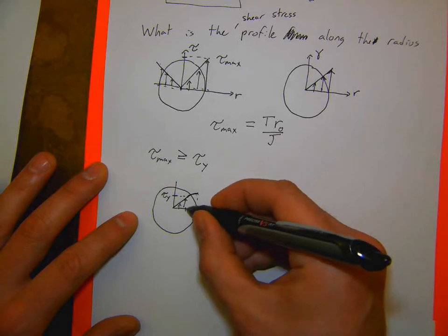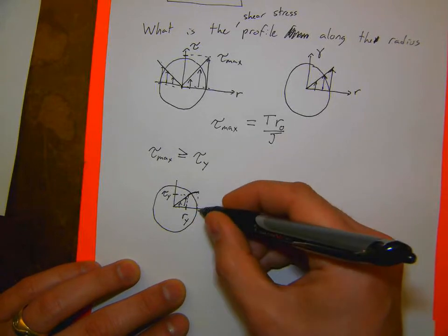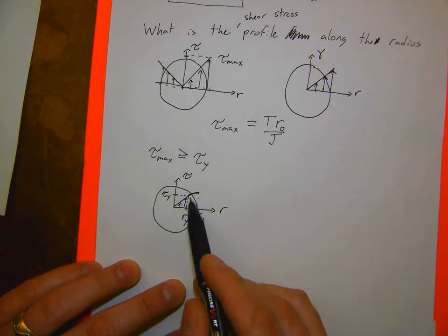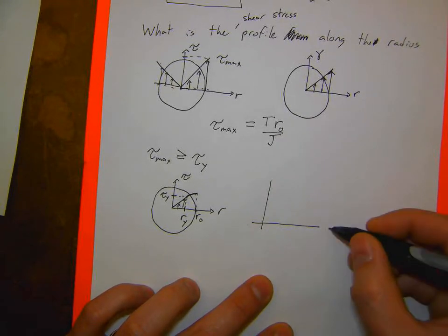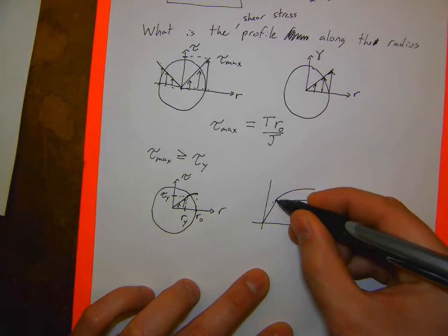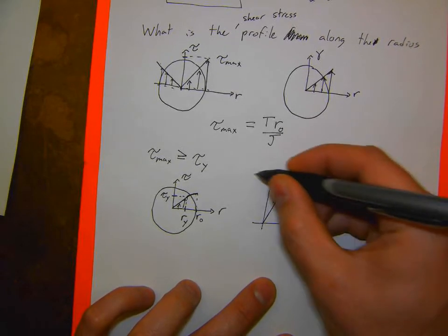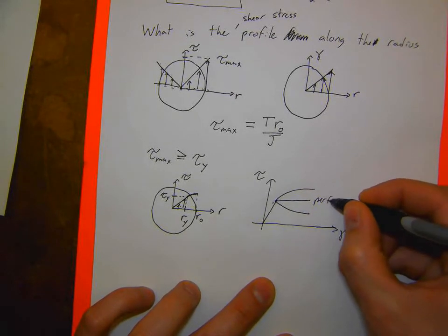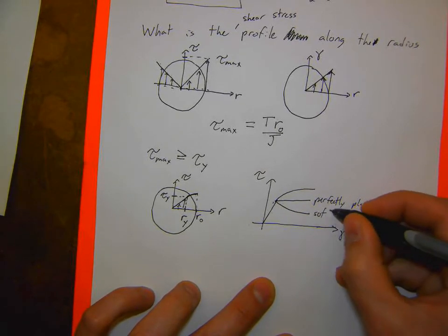So starting at some internal radius, which I'm going to call Ry, my yield radius, before I hit my R naught, it'll start plastically deforming. And the way that it behaves after that plastic deformation depends on whether the material is hardening, softening, elastic, perfectly plastic. So this is my shear versus gamma: perfectly plastic, softening,